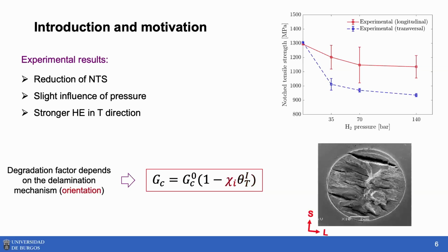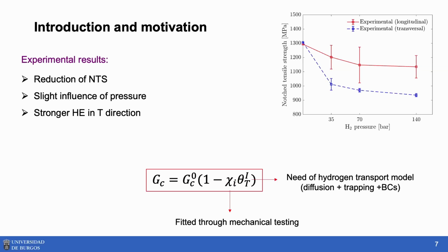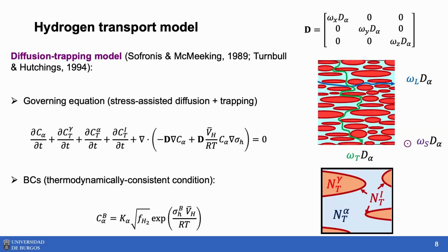Finally, we are not fitting this degradation factor from DFT. We are fitting this value experimentally, and it should be dependent on the delamination. You can see here a cross-section of the notch specimen. We have very strong delamination, so this degradation factor should be dependent on the orientation. The Chi degradation factor will be fitted through testing, and the occupancy of the interfaces will be locally calculated using finite element modeling, a local hydrogen transport model. This is the overview of the transport model. This is not our idea.